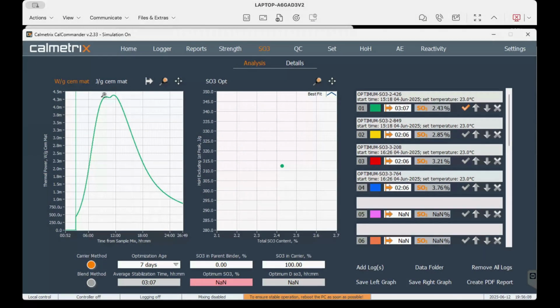Generally when it's before the main peak, it's just flat. It's like one single peak. If you look closely, you might see a little bump before, but sometimes not even that. If you see just one peak like this, not a double peak and nothing after that, very smooth, then it means the depletion is before.